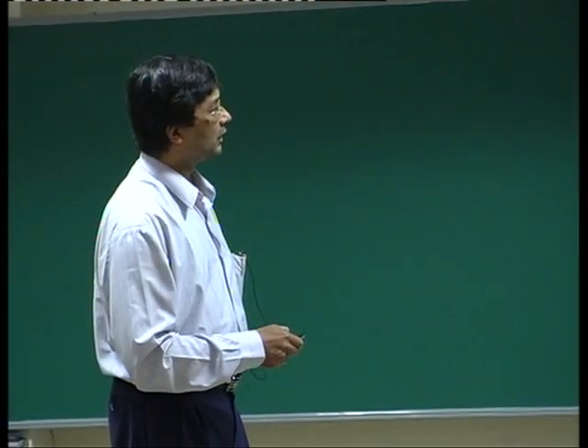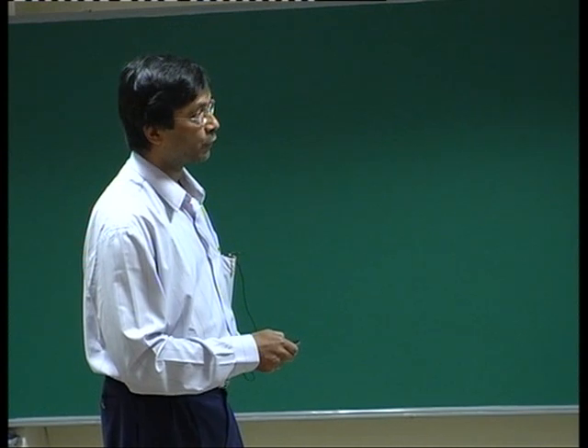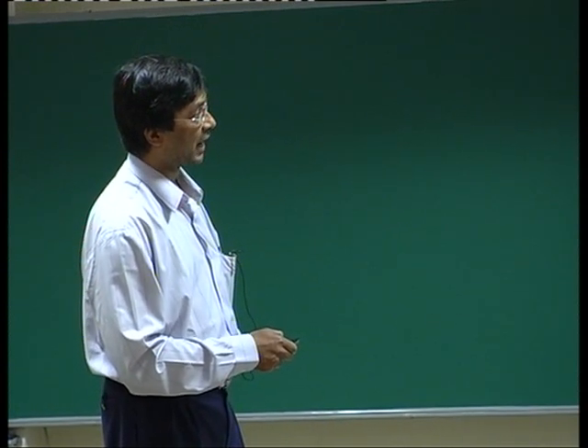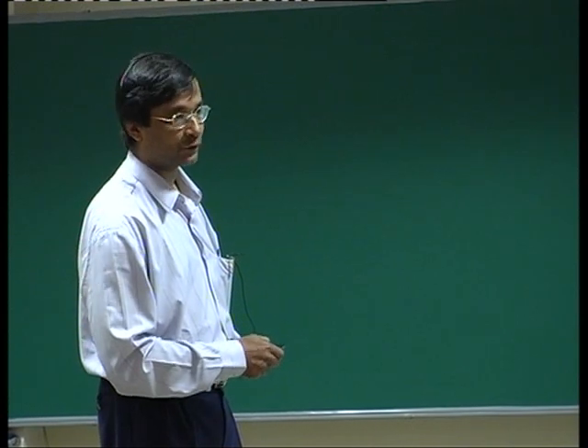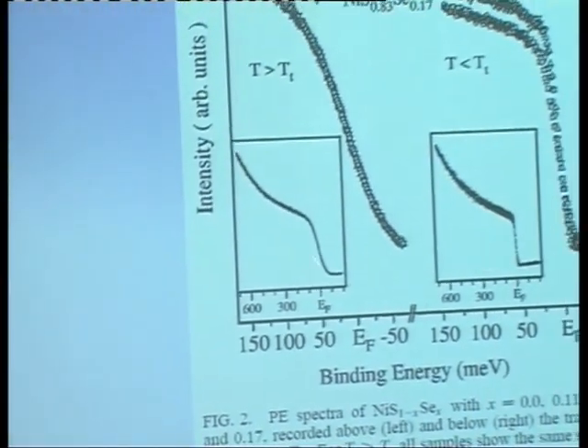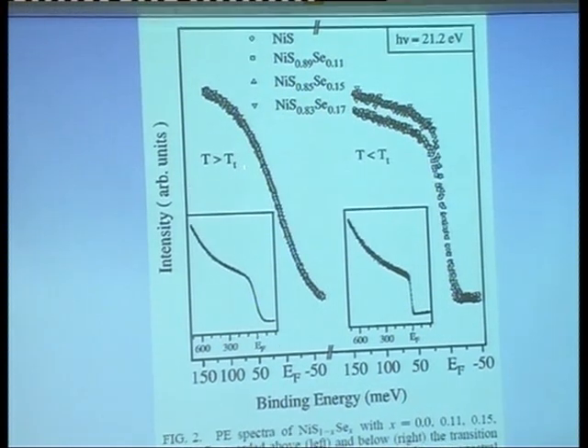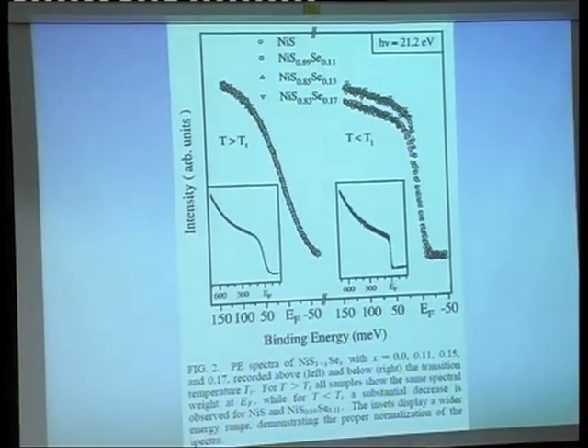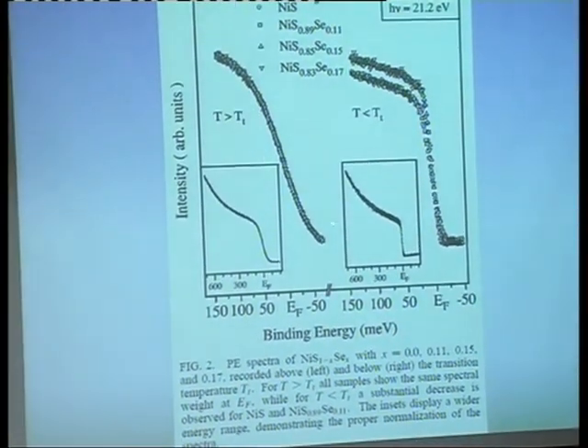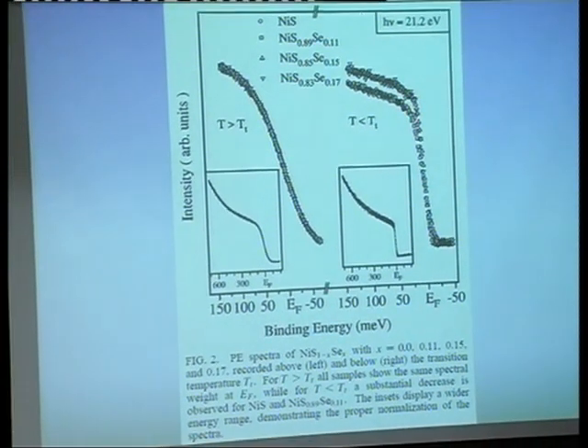We looked at it a bit more carefully. What we did, these are the 4 samples. These two show the transition. This is very close to the phase boundary with respect to the composition that would still have the first order transition. These two just across, and these two are always metallic, and they don't. These are at high temperature, room temperature, very highly expanded range, and we can see that if I look at the gross part, they all look the same, and even if I expand exactly at the Fermi energy, they look exactly overlapping with each other. Absolutely no distinction between them.